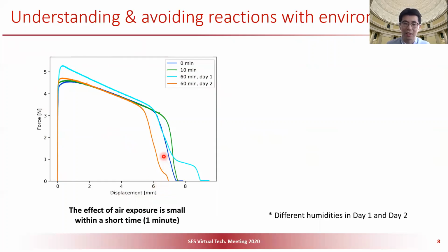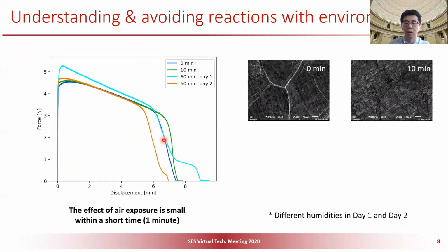However, we find that if the time is very short, like 1 minute, the difference is really small and really acceptable. So we also took the samples to see on the SEM their microstructural evolution. So immediately after cutting, everything is very, very clean and the grain boundary is very clear.